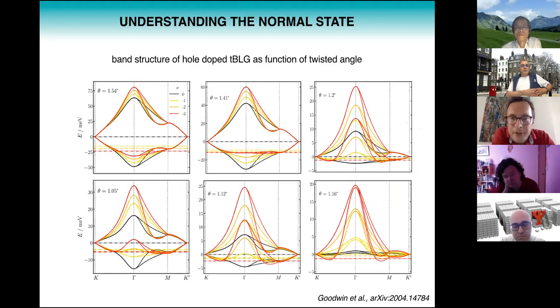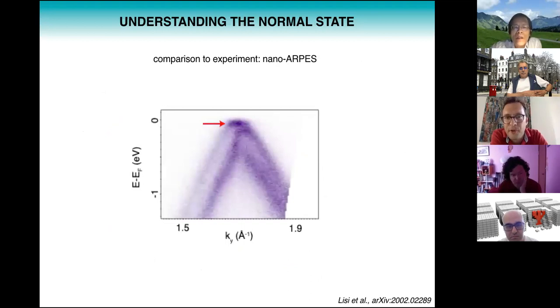So now let's also look at the evolution of the hole doped twisted bilayer as a function of twist angle. And what we see is something similar. So now the valence bands flatten, and at some twist angles, for example for nu equals -3, I get an extremely flat valence band in the gamma region. And then as I go closer to the magic angle, I get this inversion of the band structure, which again is not predicted by non-interacting tight binding theory. So again, the key lesson is that analyzing the effect of electron-electron interactions in the normal state is quite relevant and gives us new insights.